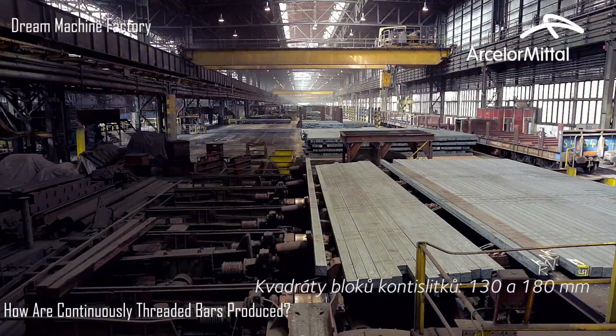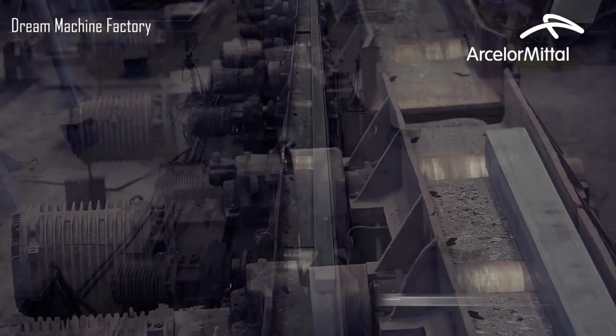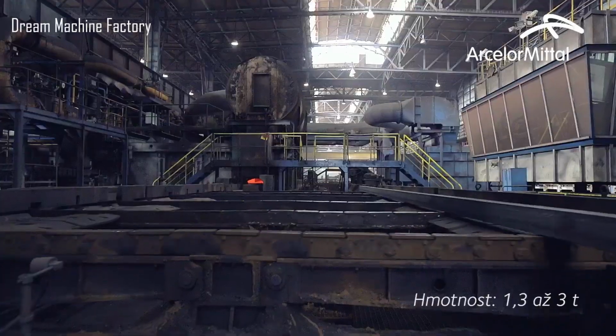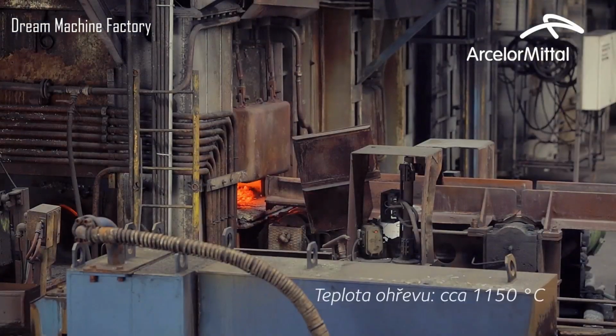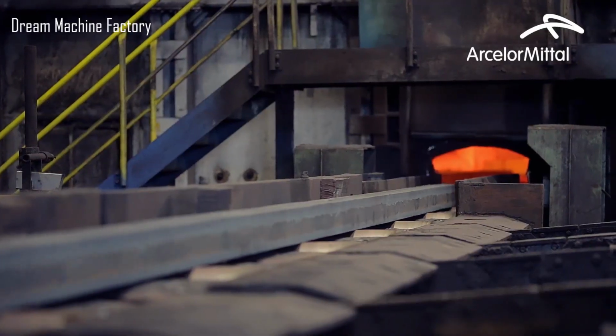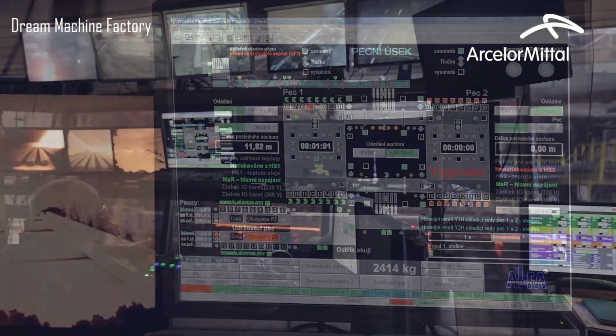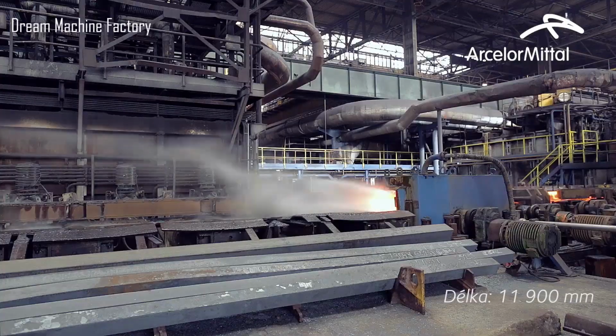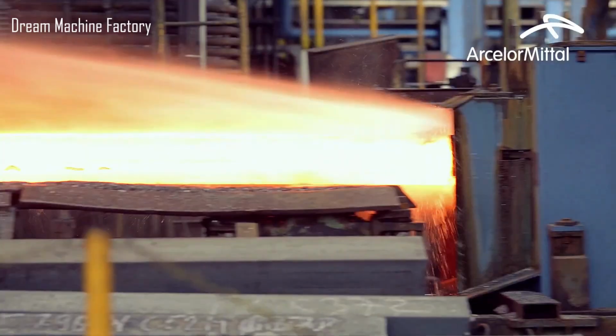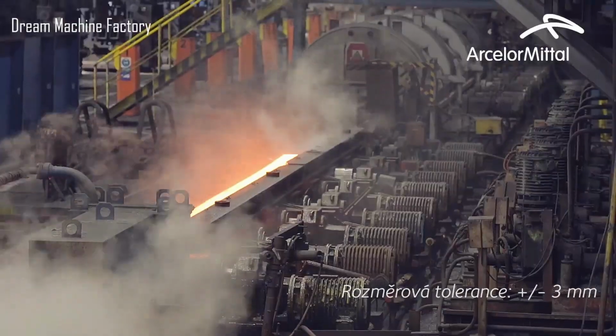The continuously cast billets are square blocks measuring 130 or 180 millimeters, weighing 1.3 to 3 tons, heated to approximately 1,150 degrees Celsius, length 11,900 millimeters, with dimensional tolerance plus or minus 3 millimeters.